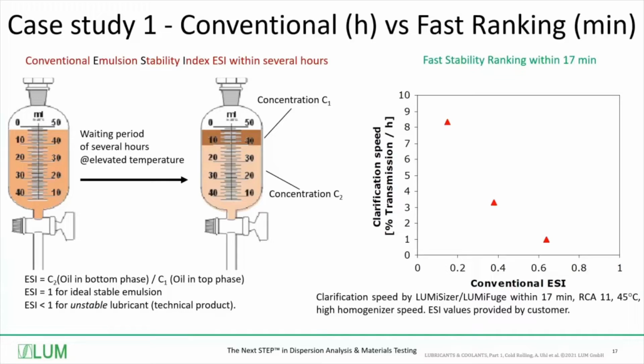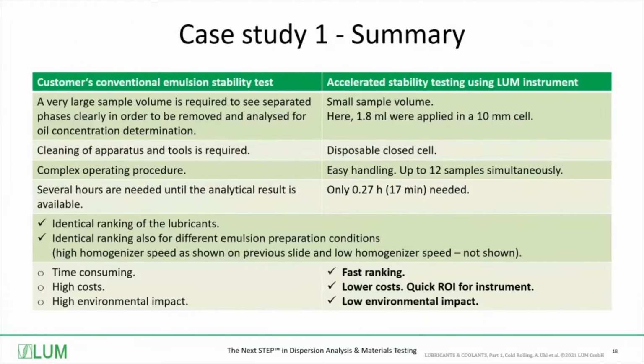It is the identical ranking obtained now after 17 minutes, 11 times accelerated, and compared at the same temperature of 45 Celsius. It gives an identical ranking of the lubricants also under different emulsion preparation conditions, which were not shown on the previous slide.